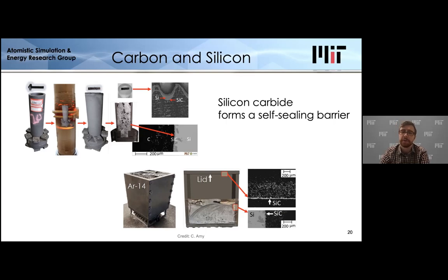So we tested this both in a small situation, on the order of 1 inch in diameter in an induction furnace, and then we also tested it in a larger tank. This AXF-5Q, or similar grade, is a reference for the grade of graphite we used, which is very important. If it's too porous graphite, then that layer is unable to form quickly enough, and a lot of silicon is able to penetrate deeply into the carbon. And in both of these cases, a protective silicon carbide layer was formed, and it prevented any more silicon from reacting with the carbon. So far, so good. Everything looks like it's working out. It looks like we can contain the silicon and carbon, and it forms a protective layer, and we have no problems.